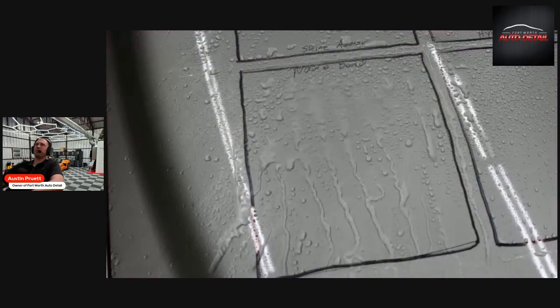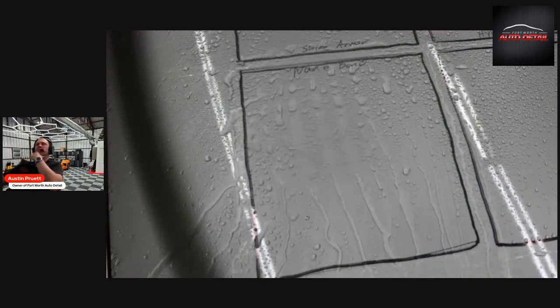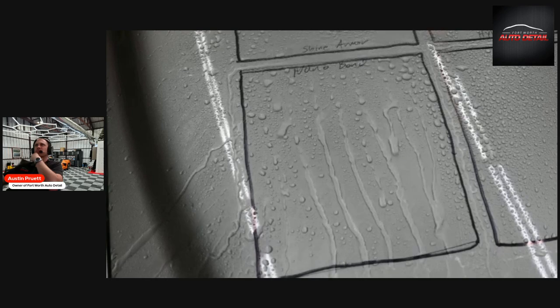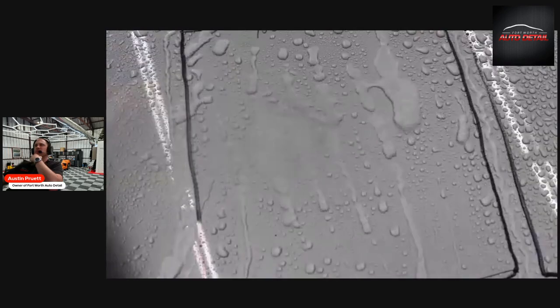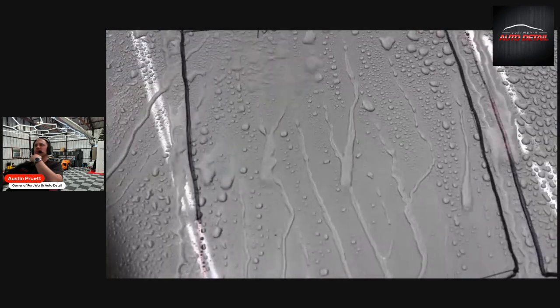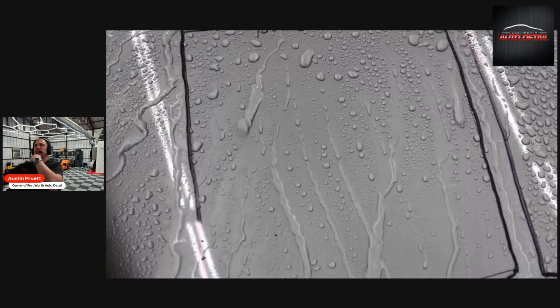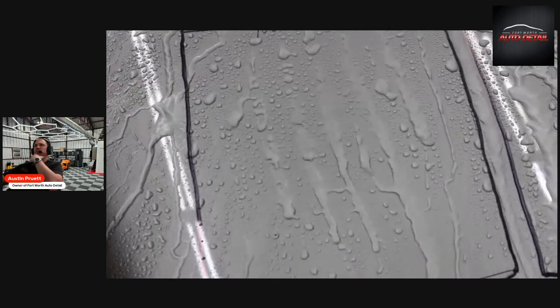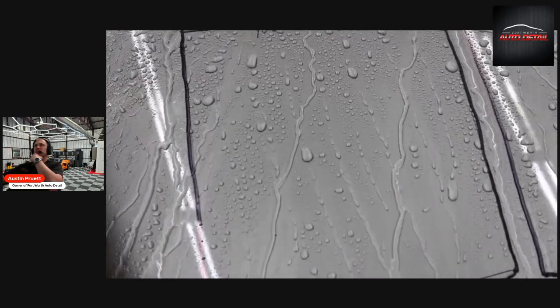And the Nanobond is performing well with the water beading and no sheets of water forming. There appears to be a vertical water flow pattern which indicates an inconsistent finish with the Nanobond coating. I did follow the manufacturer's instructions and waited 1.5 minutes before wiping and polishing the coating, but that may have been a little too long.